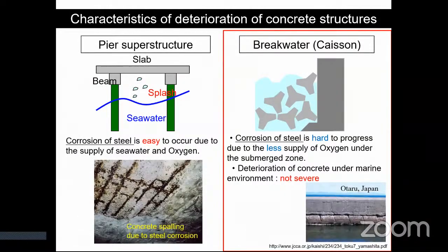On the other hand, in the case of caisson, corrosion of steel is hard to progress due to the less supply of oxygen under the submerged zone. Here, deterioration of concrete itself is not so severe in the marine environment.